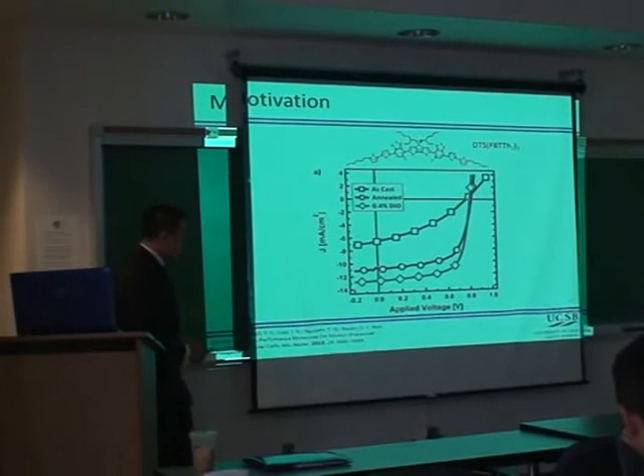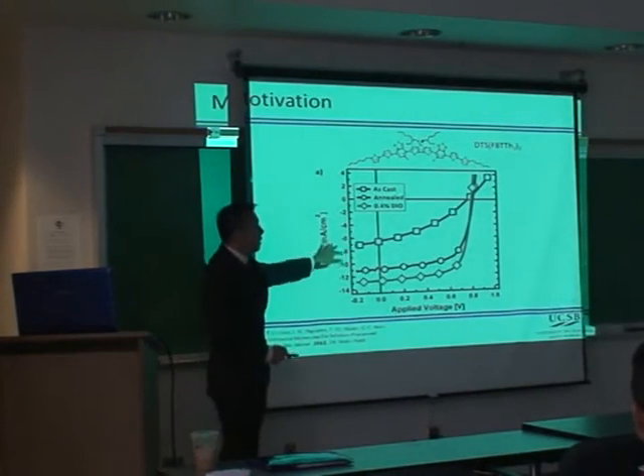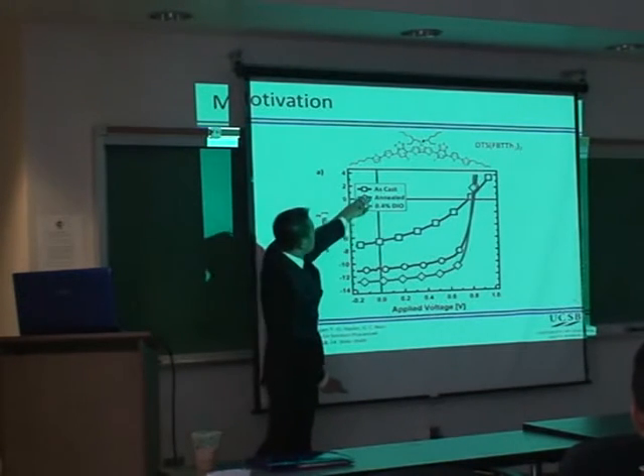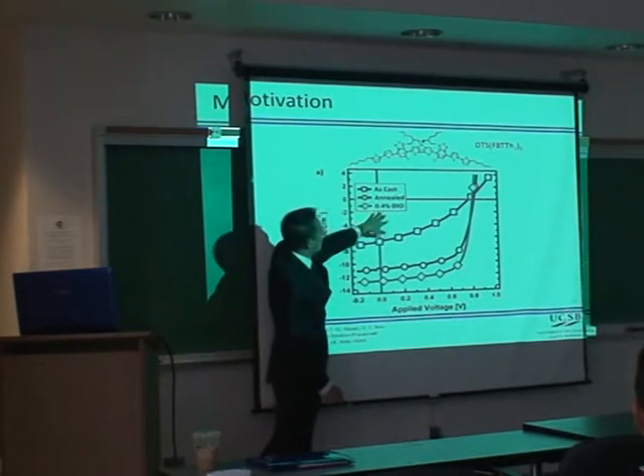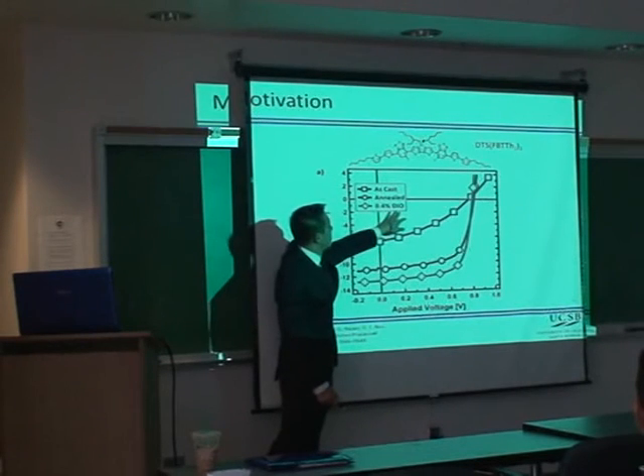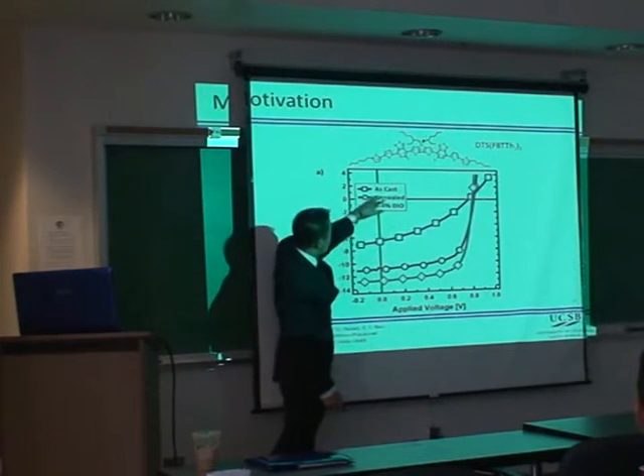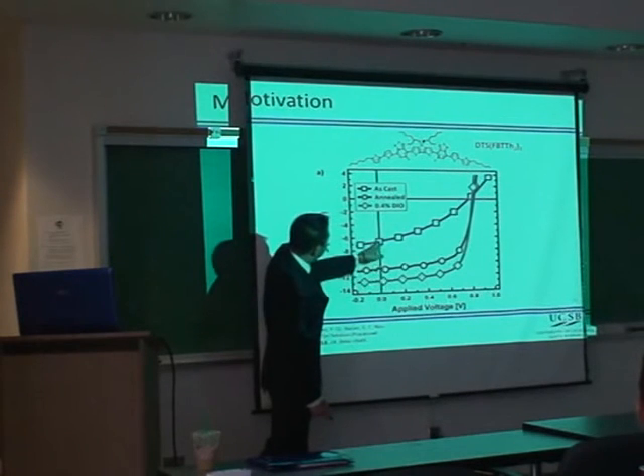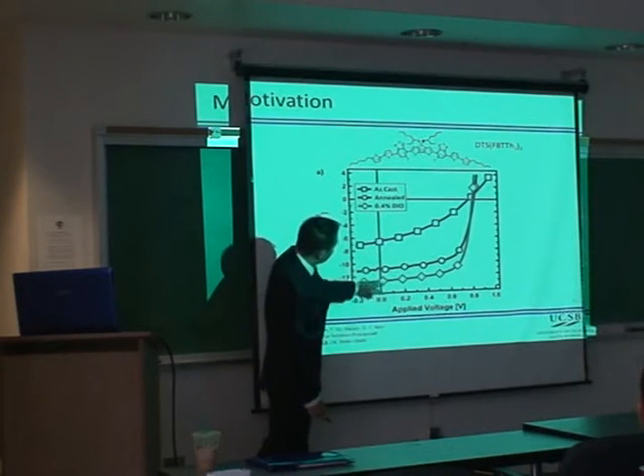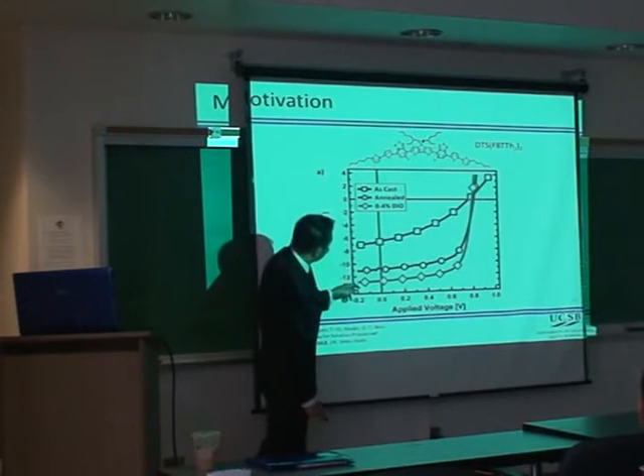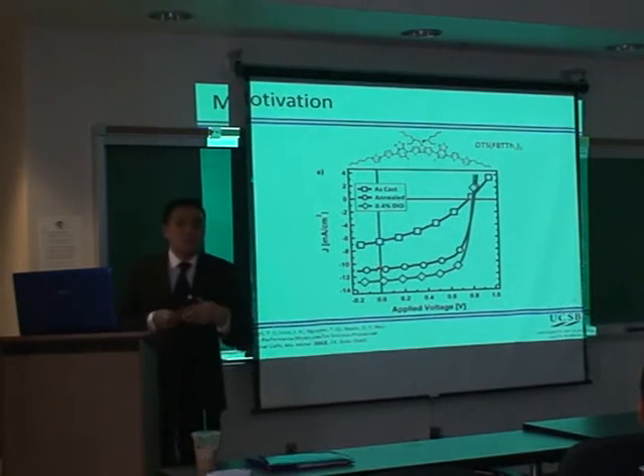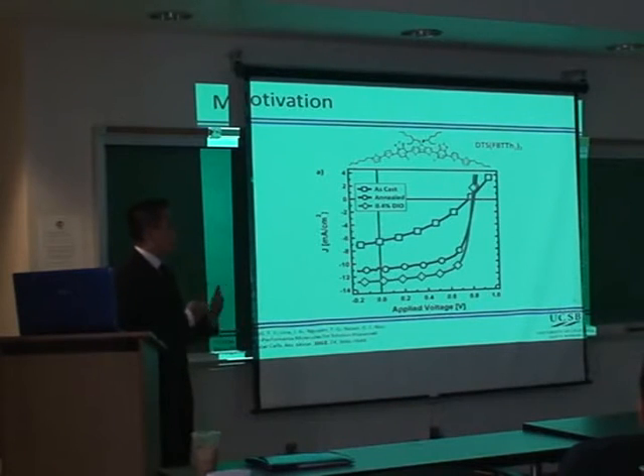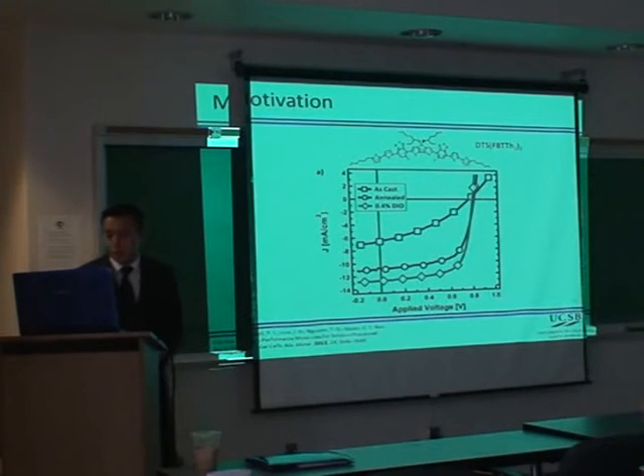So in the field of organic semiconductors, there are actually a lot of studies that have shown that when you process a film with a high boiling point solvent, such as diiodooctane, there's an increase in the current generated. For example, this blue going to this yellowish goes from 7 to 13. And most of the studies actually study how that affects charge transport and charge generation. There are no studies about how that affects the exciton diffusion rate. So that was one of the questions I wanted to answer. How does that affect that part?